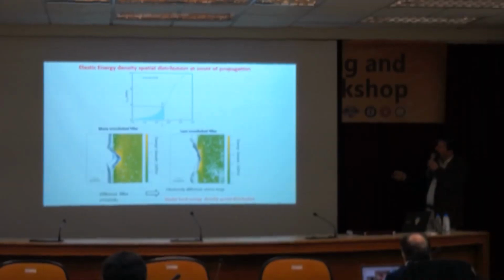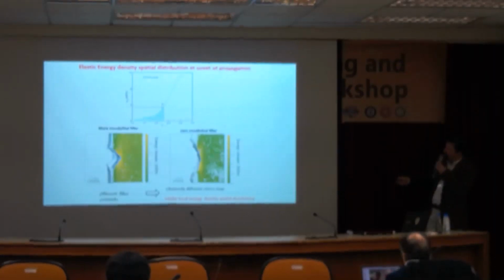Another thing that we can get from the stress is the strain energy. We could get it from the strain, but for strain hardening material, it's actually more accurate to get it from the stress. And here we can see that if we actually measure the strain energy, these two materials actually do break at a fairly similar level of strain energy close to the crack.